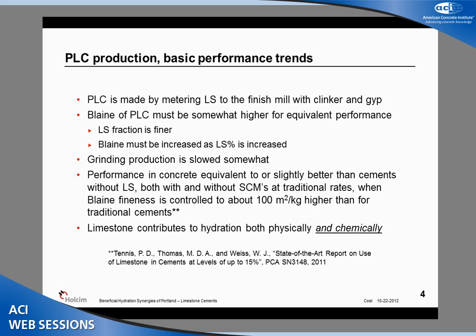I would argue, and I think I'll show a little bit later in the presentation, that when we do this, we may actually be seeing very fine limestone, but Portland cement clinker particles that are no longer quite as fine as those in the ordinary Portland cement. So this is a very complex relationship.